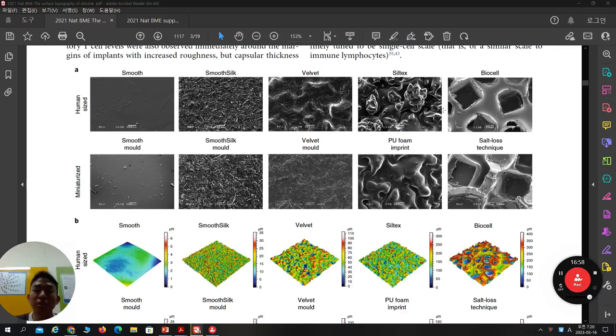So the basic concept is how you can make different surfaces of the PDMS. The strategy is that you can make different surfaces of the mold. Let's say when you want to use a Teflon mold, you treat the Teflon mold surface, like nano surface, micro surface, and then if you pour the PDMS silicone on that mold, you can get this kind of different surface roughness. This is the basic concept. When you use glass, maybe we can get an absolutely smooth surface. But when you use a differently roughened surface of the mold, depending on that, you can get the negative impression of this surface.